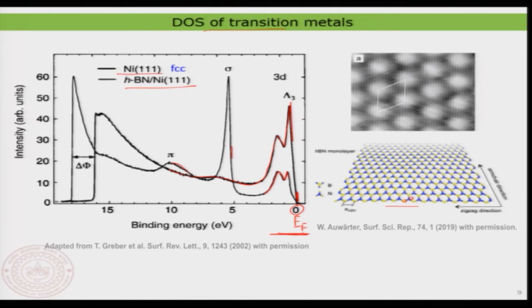and you can use it for understanding their electronic structure in general. You can also, for example, compare the change in work function. That's something interesting, because if you know the photon energy, as I told you in the beginning, then you can also calculate the work function if the work function is unknown. Now, when you deposit the boron nitride on the nickel 111 surface, you clearly see that there is a change in the work function. This change is due to the fact that the material property itself is changing. That's something you can also measure in ultraviolet photoelectron spectroscopy, clearly. That's something that you can do with this kind of spectroscopy.